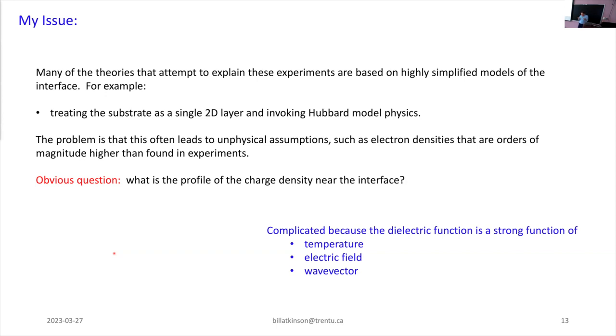And so this raised for me this very basic question about what is the profile of the charge density near the interface. And we weren't the first people to think about this or the first people to work on this. We were the first people to really think about temperature dependence. And temperature dependence is highly non-trivial because, as I showed you already, the dielectric function is a strong function of temperature. Remember I had that plot of one over the dielectric function versus temperature? It changes by almost two orders of magnitude between room temperature and zero Kelvin. So that's an enormous change in the dielectric function. The dielectric function is also a strong function of electric field, and it's a strong function of wave vector. So all of these things are going to modulate the profile of your charge density interface.